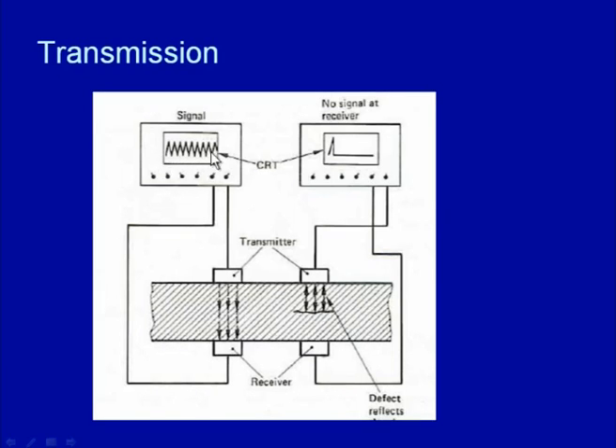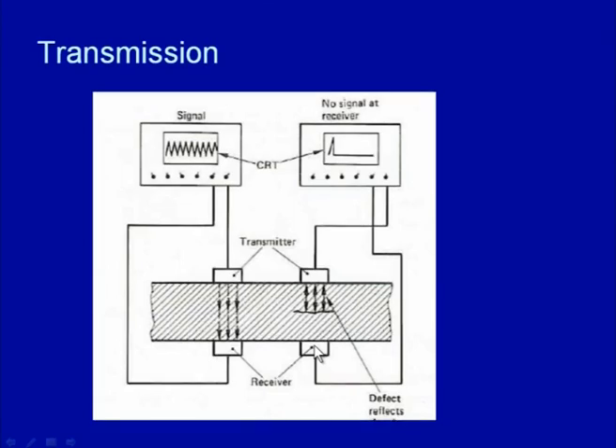So, continuous presence of these vibrations in the oscilloscope indicates no defect, but when it comes across a discontinuity like this, these are being transmitted but not received on the other side. So, no vibrations will be received at the receiving end, and the receiving end will not give any signal in the oscilloscope. It will get just one peak, and no other peak is observed. So, this suggests that some sort of big defect is present in the component.